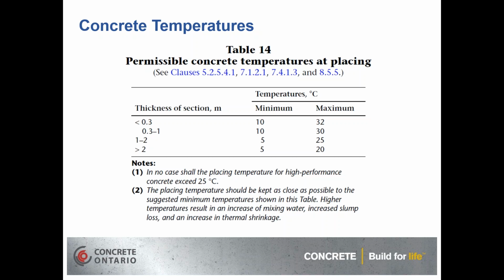CSA Table 14 defines the permissible concrete temperatures of placement, and it looks at the minimum thicknesses of concrete sections or elements. So most of our construction is either less than 300 millimeters or between 300 millimeters and 1 meter. The minimum concrete temperature placement to ensure proper setting, strength and durability is 10 degrees C, while the maximums vary between 30 and 32. Once the element gets thicker, now you need to worry about the heat generated in the core of the element. So lower maximum and minimum temperatures are typically specified, but you'll notice there that we don't go below 5 degrees C, trying to keep those temperatures above the freezing point.